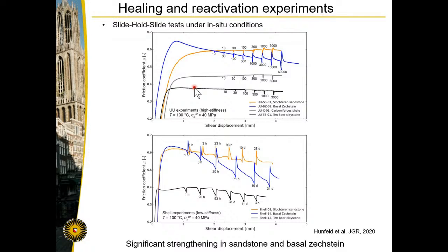And what you can see, first of all, is the same contrast in coefficient of friction as in the previous experiment. But we also see a very different resliding behavior. So we have the clay-rich lithologies. They're down here, and they show almost no change after a hold period. Whereas the orange and blue curves show this distinct peak upon resliding. And that peak is the re-strengthening that occurs when the fault is inactive.